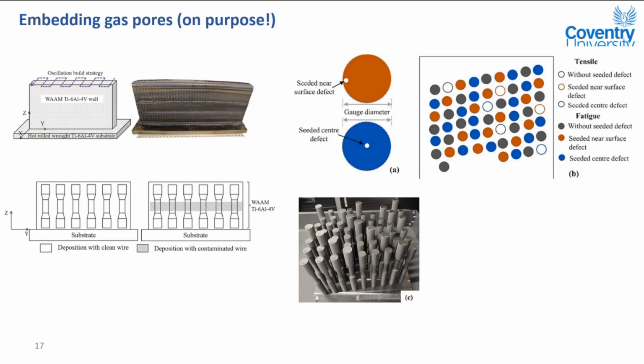So for the powder bed fusion, I participated in a project by the Manufacturing Technology Center, a catapult in Coventry. They actually use laser powder bed fusion, so that is a near net shape build. They build so many, and these orange colors are where we embed one pore, they call a seeded pore, by computer-aided design. So in that layer, they don't print material. Then they also, in blue, print defects in the middle. These are not lack of fusion or keyhole. These are entrapped gas pores.